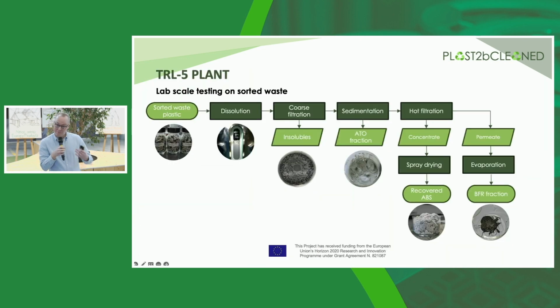I'm going to show you the same thing that Lucy showed you, but in this case, it wasn't on reference material, but on sorted waste. So it's hand-picked waste from CRT back screens. As you can see, we start with the sorted waste. We do the dissolution, we do the coarse filtration. Here again, we have about 2% insoluble material. Unfortunately, truth be told, the antimony trioxide fraction is still roadworks ahead for us. It doesn't look as nice as the results we had on the reference material.